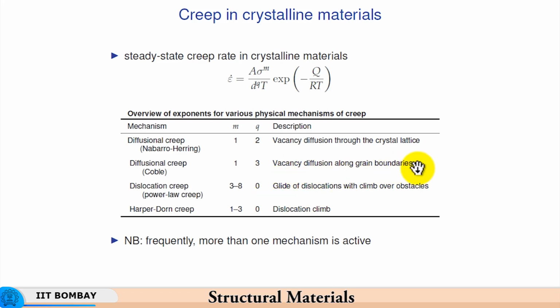So, that is why we say that vacancy diffuses through the crystal lattice. Vacancies can also diffuse along the grain boundaries. Basically, grain boundaries are the regions of maximum disorder. The arrangement of atoms is not orderly, and so it promotes diffusion, because the atoms are at higher energy levels as well. So, the relative attraction between the atoms can be overcome more easily, and therefore the diffusion along grain boundaries also becomes very easy, and so the dependence is cube. That is because diffusion along grain boundaries depends on the area of the grain boundary network. So, if the area of the grain boundary network is very high, then the diffusion paths are also relatively smaller,